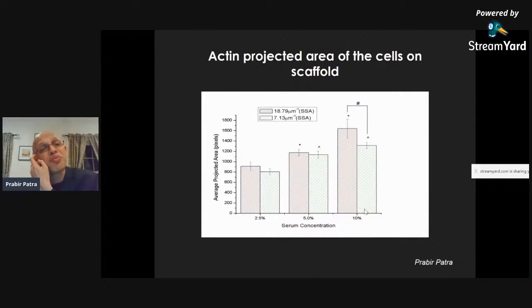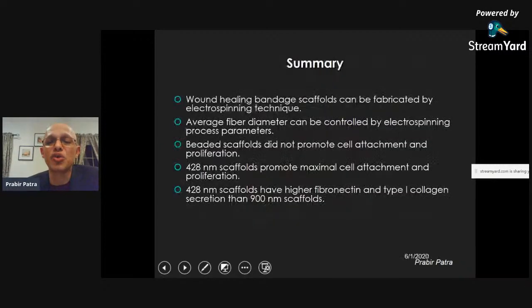We also saw the role of specific surface area over volume. As the fibers are small in size, this specific surface area plays a very important role for the cells to grow and form tissues. So you can tell, the smaller the fibers, the better it is for the cells to grow.